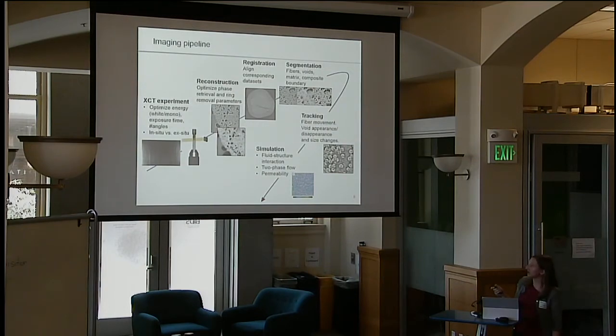The next step is then to optimize the reconstruction, to remove artifacts, and optimize phase retrieval parameters, which can create very different images, which affects the later stage of segmentation. The next step would be to register the data sets so they can be aligned in 3D, so we can correlate the movement of the features over time. And then finally, segmentation, where we're interested in identifying the fibers, the voids, the matrix, the boundary of the specimen, so that we can measure the properties of each of these features.